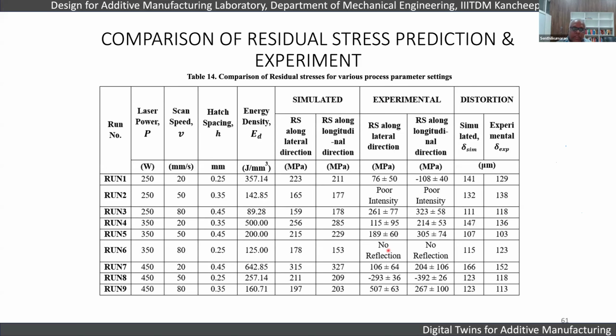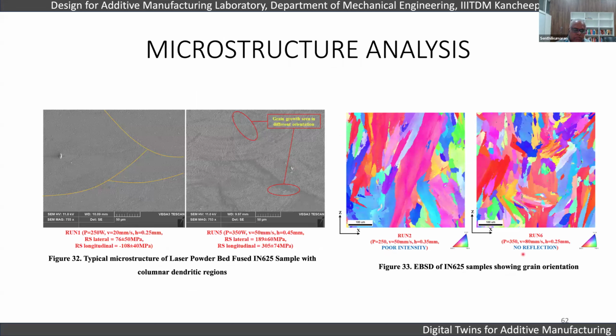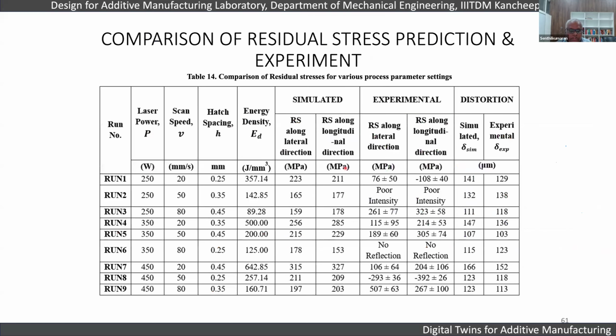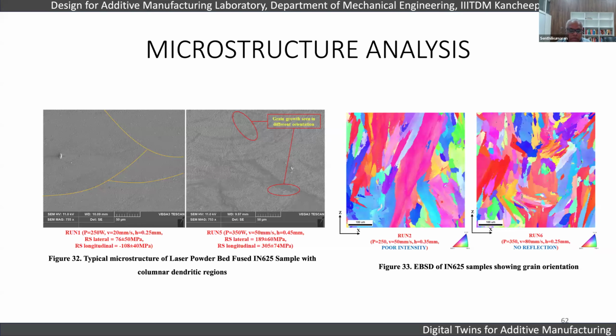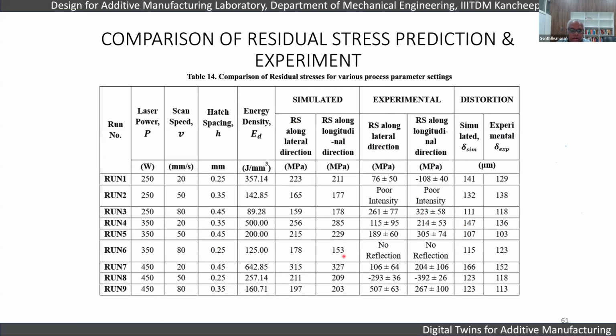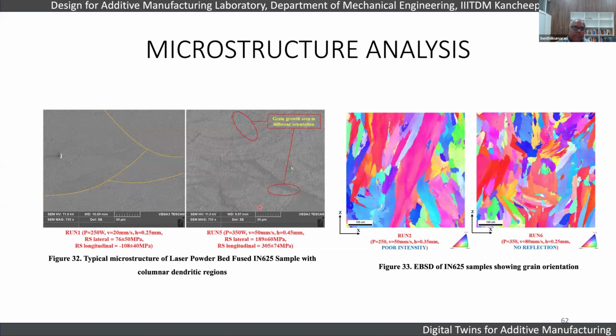Then we tried to understand in more depth why the simulations fail. We did EBSD for two samples, run 2 and run 6. Run 2 has a poor intensity, and for run 6 we could not get any reflections. We found some issues with the grain orientations, because looking at the laser power signature, we could see that the energy density is much lower here. These are the two parts with much lower energy density, where we found that solidification has not happened properly. The grain orientation is very random, which helped us understand that residual stress measurement for lower energy density becomes much more difficult, and it is difficult to simulate in the software.